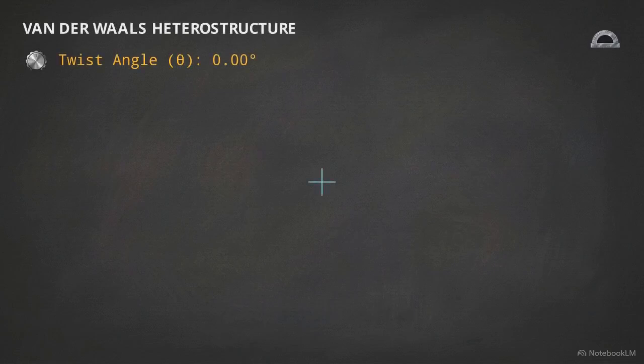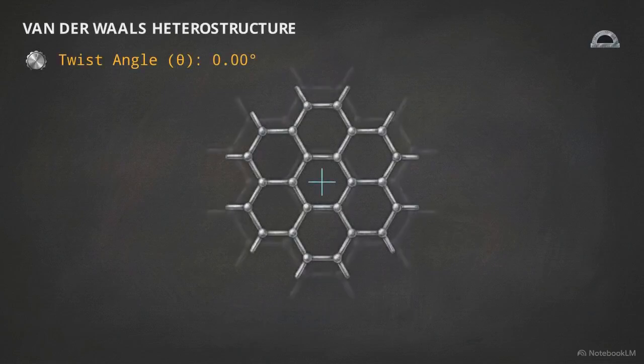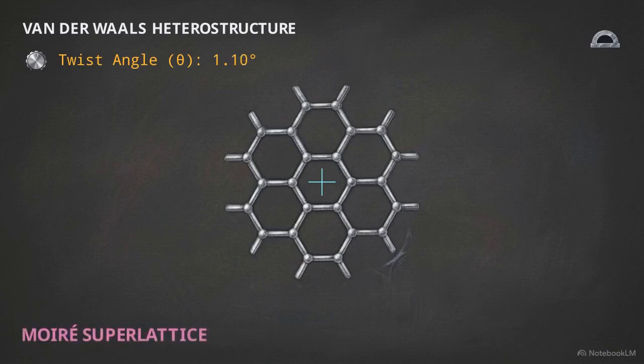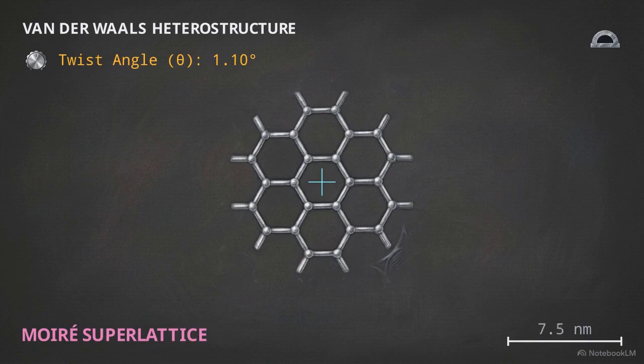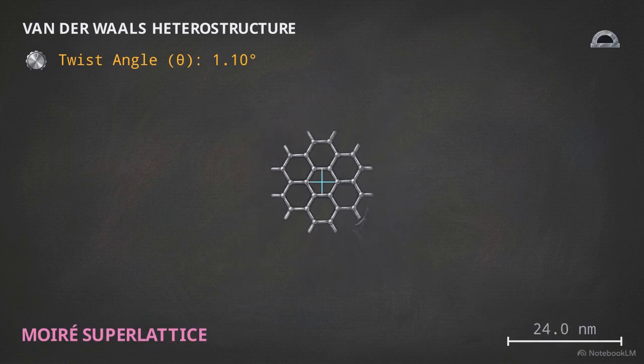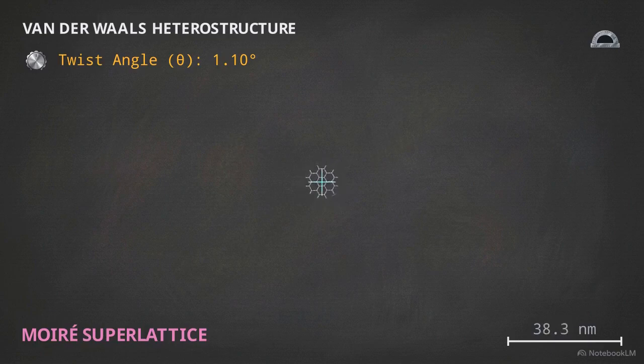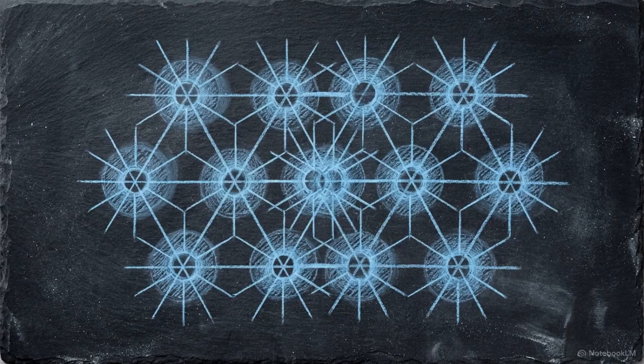The process begins with a van der Waals heterostructure, stacking two distinct two-dimensional sheets of graphene directly on top of one another. By twisting the top layer slightly out of alignment, a new emergent geometry appears. This creates a Moiré superlattice. It is a periodic pattern with a length scale orders of magnitude larger than the individual carbon atoms underneath it. This geometric trick creates a metamaterial, setting the physical stage to rewrite how electrons move.